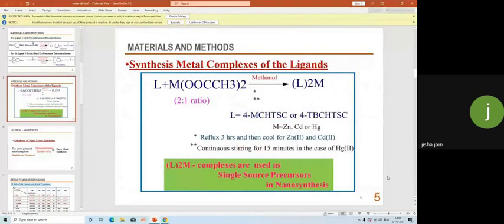Then synthesis of metal complexes of the ligands. For that, methanolic solutions of the ligand and metal acetates are taken in a 2:1 ratio. The corresponding metal complexes get precipitated. The ligands are the previously synthesized 4-methyl cyclohexanone thiosemicarbazone and 4-tertiary butyl cyclohexanone thiosemicarbazone, and the metal salts taken are the acetate salts of zinc, cadmium, and mercury. The procedure used for zinc and cadmium complexes is that the reaction mixture is refluxed for 3 hours on a water bath and then cooled slowly. For the mercury complex, only continuous stirring for 15 minutes is required for precipitation. Then these metal complexes are used as single source precursors in nanosynthesis.